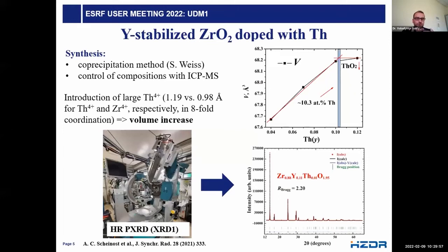We want to incorporate thorium in this matrix. What can we expect? Thorium 4+ is larger than zirconium 4+. So we expect that the unit cell will be expanded, and this is indeed what we observe. Up to roughly 10 atomic percent of thorium, when you introduce it, the unit volume expands, and then you have a precipitation of thorium oxide. So the solubility limit of thorium for the tetragonal phase is about 10 atomic percent. We would also like to know what happens in this region when you introduce thorium to the structure of the system. For this reason, we synthesized more samples with finer steps in this region, and then we performed high-resolution diffraction studies on the Rossendorf beamline.